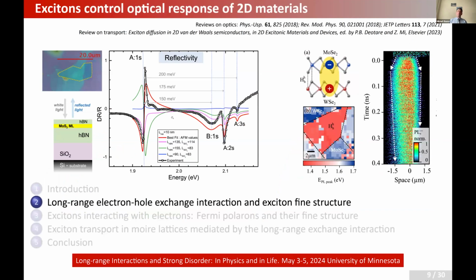I only want to mention that these excitons do dominate the optical response, as seen, for instance, in this reflectivity plot. There you have the ground excitonic states, excited states, and also another excitonic state that comes from the spin-orbit splitting of bands. And you have relatively good agreement between the observed spectra and theoretical modeling based on this relatively simple Schrödinger equation. In addition to standard spectroscopy and time-resolved dynamics, people actively study excitonic transport, and in optical experiments you can visualize how excitons propagate. If I have time, this will also be a short part of my talk. So now let us move on.